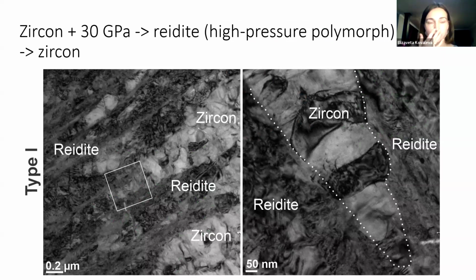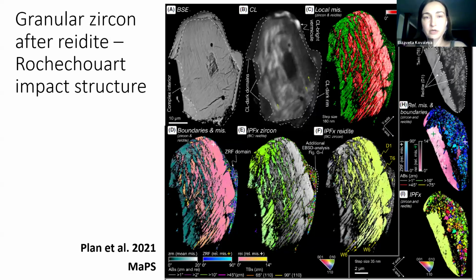Some more pretty images. This is the diffraction contrast images of the same. And on top, I just put an explanation of what happened. Zircon was subjected to high pressure. For shock pressures, it must be about 30 gigapascal. It was converted to reidite, which is a high pressure polymorph. And when the reidite pressure got released and got heated, in experiments, they had to heat it to 1200 degrees to get zircon again. So I'm just putting this experimental data. It reverted back to zircon, and these granules represent this entire history of extreme conditions. This was described in Rochechouart impact structure, also in France.